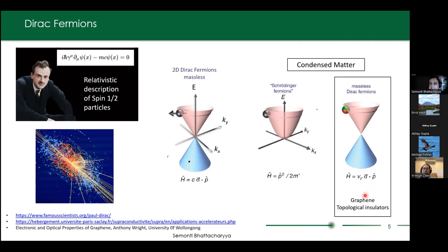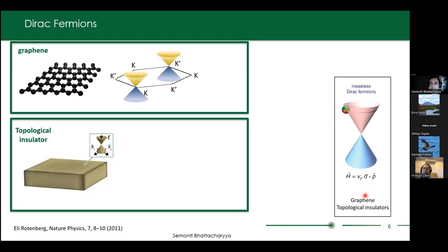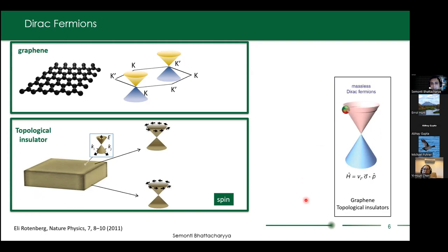In special circumstances, Dirac-like fermions appear in condensed matter systems with a Hamiltonian of the same form as massless Dirac fermions, where Vf is the Fermi velocity. These systems are mainly graphene and topological insulators. In graphene, Dirac fermions appear at the corners of the Brillouin zone, the K and K-prime points. In topological insulators, they appear at the surfaces as a result of the topological nature of the bulk bands. The sigma denotes actual spin for topological insulators, leading to a chiral spin structure, whereas for graphene it refers to pseudospin arising from the two sub-lattices.